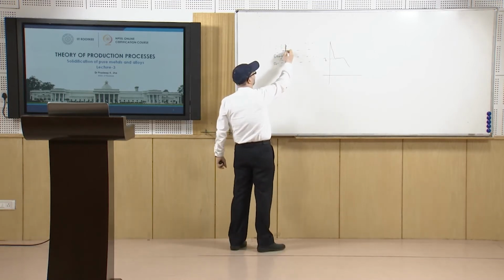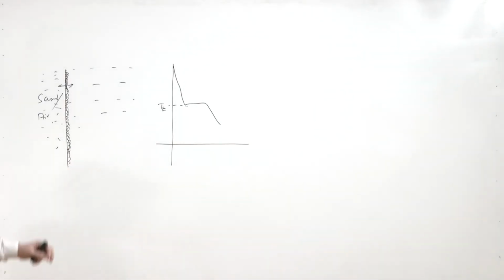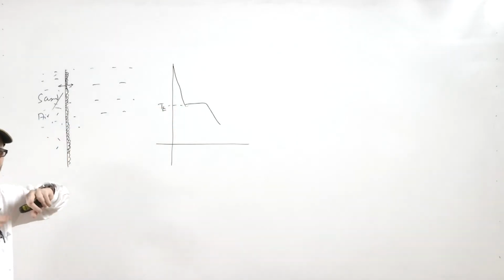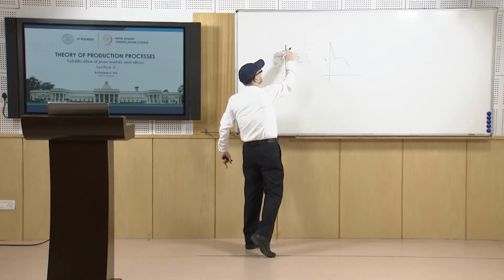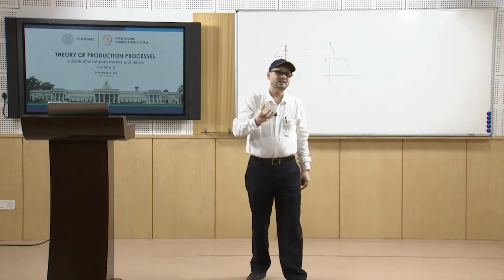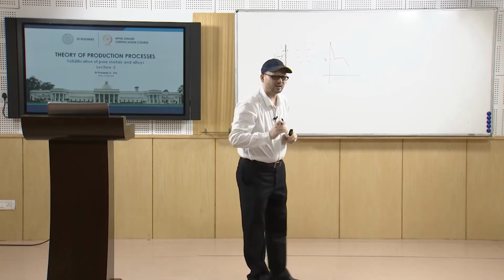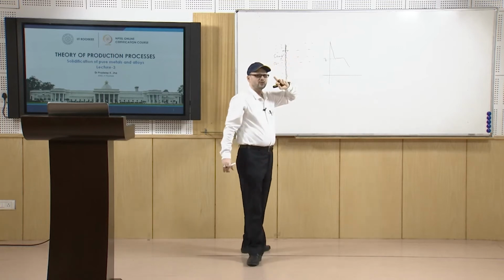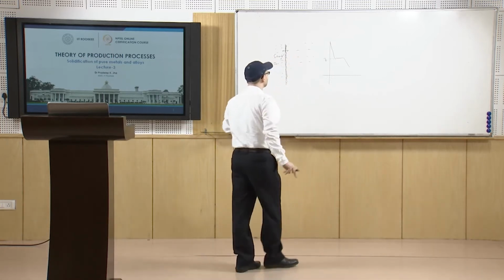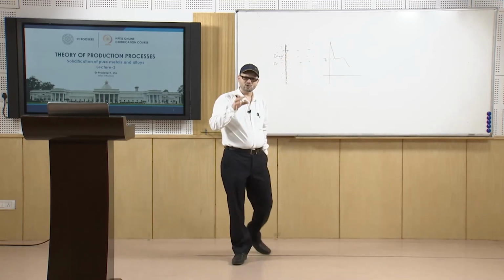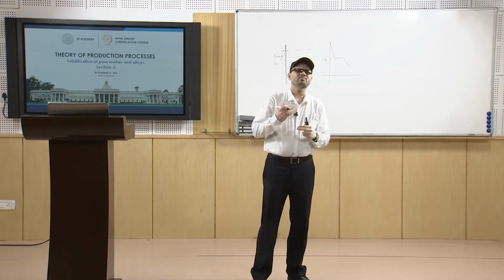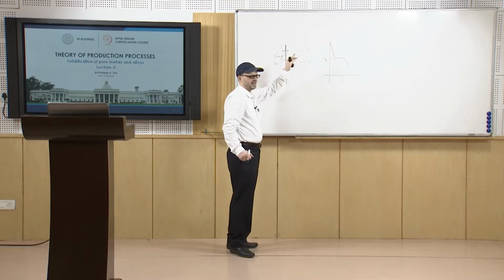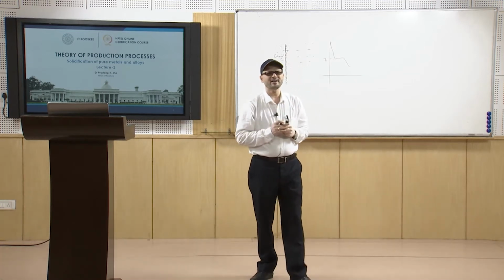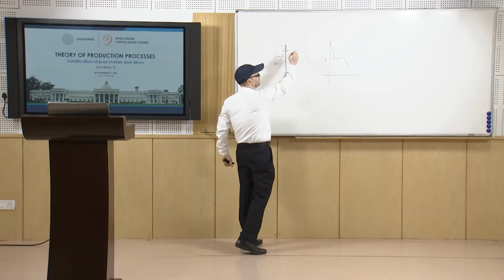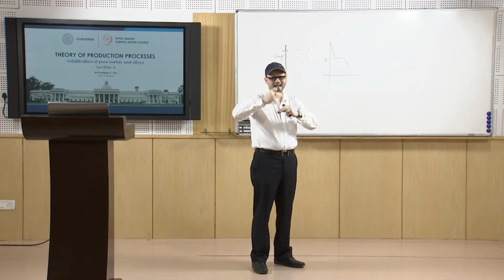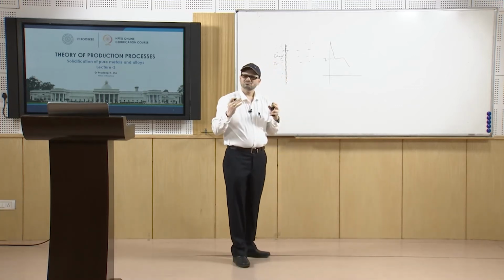Now, the heat flow is primarily going in this direction. Since the undercooling experienced, or the temperature drop here, is delayed and is less, it will be closer to the equilibrium temperature. In that case the nucleation does not remain predominant. In the early stages of the solidification the nucleation is predominant, but as time progresses, because of the heat release and the equalization of the temperature in the remaining area, the nucleation does not remain predominant,